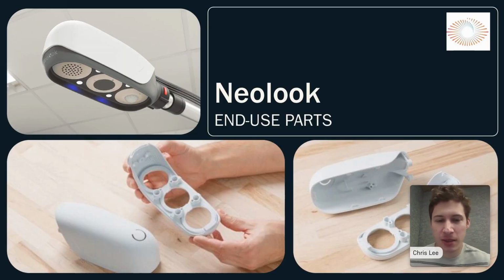This customer here, obviously not in the medical space per se, but they are producing these housings, covers in Nylon 12 white. In order for them to get the brightest white possible, they are utilizing a Fuse 1 Plus 30 watt and the inert gas via nitrogen. What that nitrogen will do is push out all the bad stuff, reduce oxidation, and have the powder and the end process and parts be a lot more white and obviously more appropriate for their use here to look a little bit more professional and things like that.